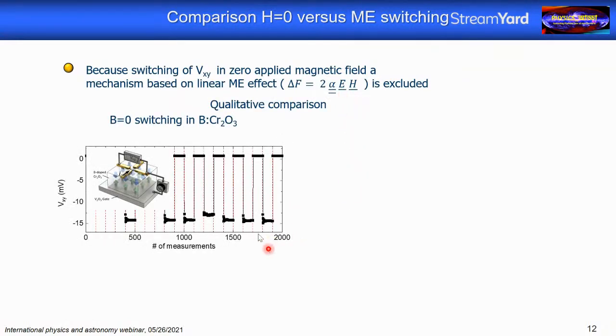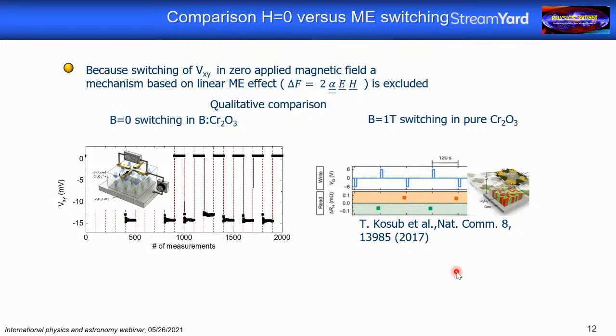So let's have a comparison between our result in the boron-doped material and results that have been obtained by a group in Germany some time ago in pure chromia. And here you see that this is really a different animal. So these folks have done the same thing. They have grown a Hall bar structure on top of pure chromia, and they were able to switch the antiferromagnetic Néel vector in pure chromia by applying gate voltages, as you see here. They were able to switch between different Hall resistance values by applying gate voltages.